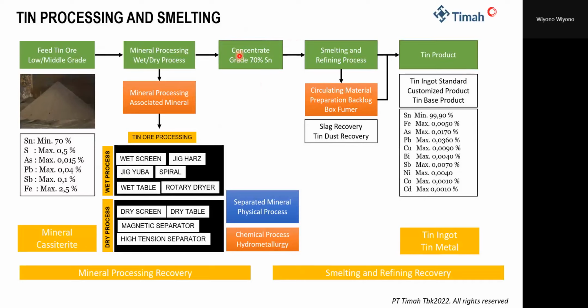When we have got the cassiterite with 70% Sn, we continue the process to smelting and refining. In Muntok, the plant of mineral processing and the smelter are different, but still in Muntok. So we deliver the tin concentrate, with a minimum grade of 70% Sn, to the smelter, and before the tin concentrate is smelted, we do some preparation.